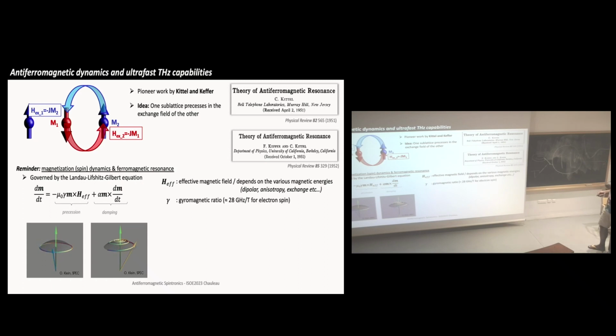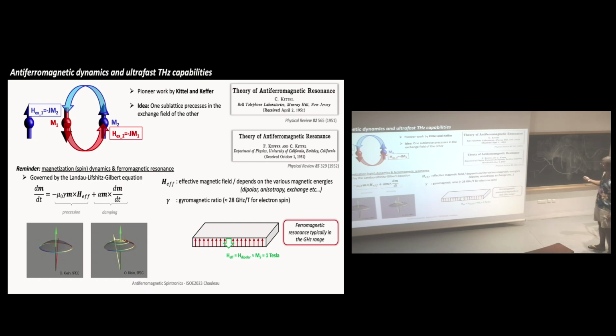But now what you have to know is that here you have a little term which is called the gyromagnetic ratio. Its value is 28 GHz per Tesla for the electron spin. So if you consider only a ferromagnet where all spins are aligned together, then you have no exchange. Exchange is zero, it's minimized. And most of what you feel is the dipolar field, which is about 1 Tesla in ferromagnets, and anisotropy, which is, let's say, 0.1 Tesla, something like this, or even less. Then typically you do 1 Tesla times 28, done. So basically, ferromagnetic resonance typically lies in the gigahertz range.